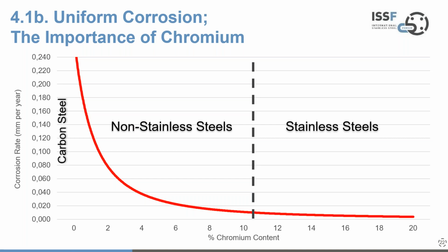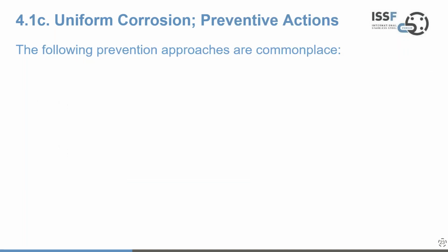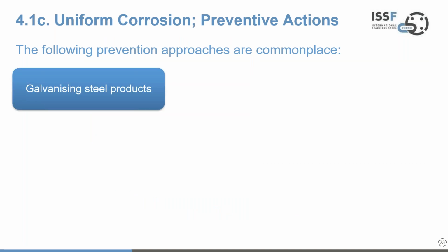And it's chromium, in this case, that forms the passive film. And particularly above 10.5% chromium, the passive film is readily formed and, as I've said, is self-repairing. So how do we prevent uniform corrosion? Well, you can do it with barrier layers, of course.